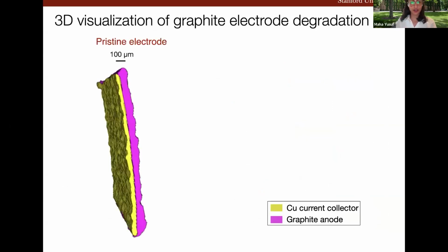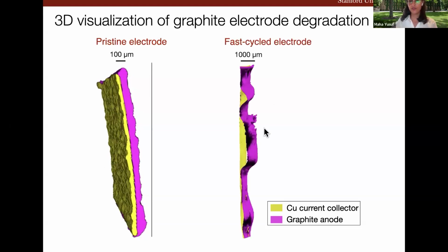And you can see here in the 3D visualization of the pristine electrode, we have copper, which is yellow, and pink, which is graphite. So we can identify both of these materials at the same time. And this visualization shows that the two strips are on top of each other with no sign of degradation. But if we compare this visualization to that of the fast cycled electrode, we can clearly see delamination of the graphite from the copper current collector.